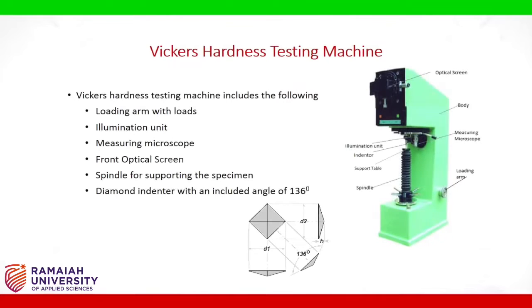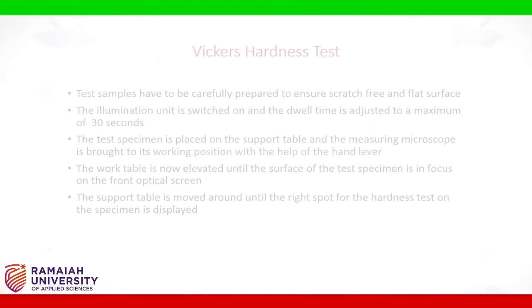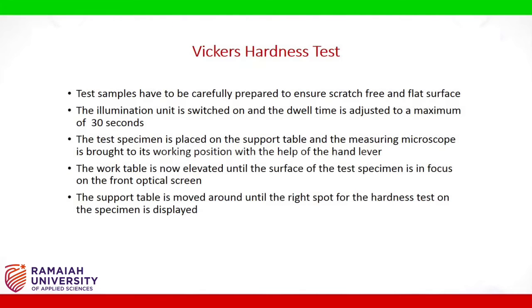Vickers hardness testing machine includes the following: loading arm with loads, illumination unit, measuring microscope, front optical screen, spindle for supporting the specimen, diamond indenter with an included angle of 136 degrees. Test samples have to be carefully prepared to ensure scratch-free and flat surface. The illumination unit is switched on and the dwell time is adjusted to a maximum of 30 seconds.